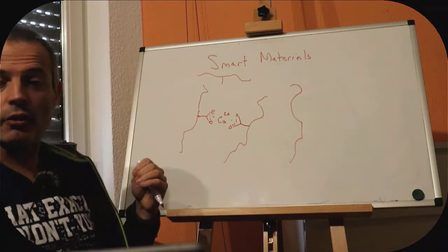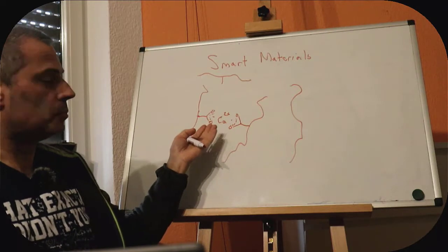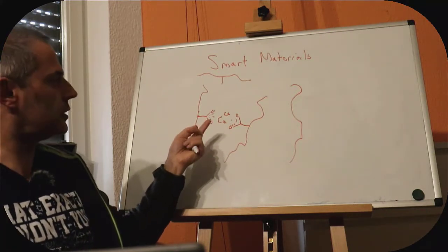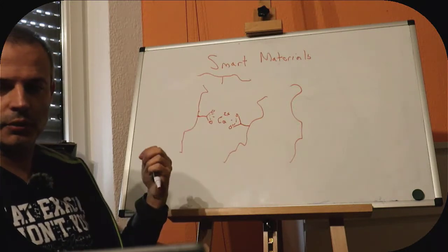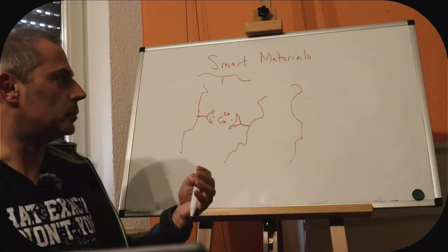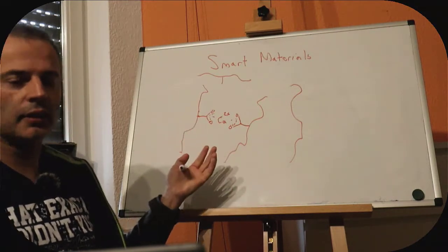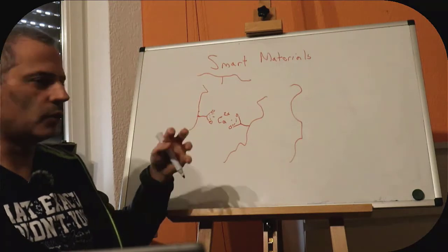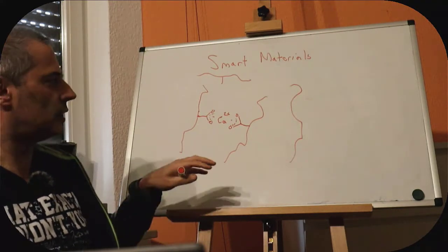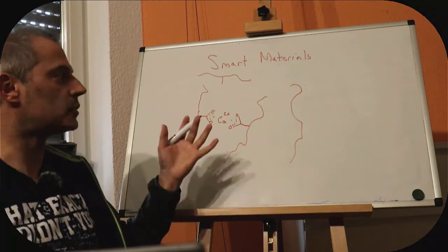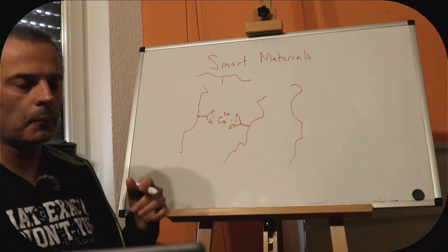In the case of blood, what we do to remove them is we add a stronger complexing agent that will pull the calcium out and hide it, and then we will need to add more calcium to cycle it again. The problem being obviously that the original calcium is still there, locked up in the original chelating agent, and so we will have a limited number of cycles, but it does behave very much like blood.